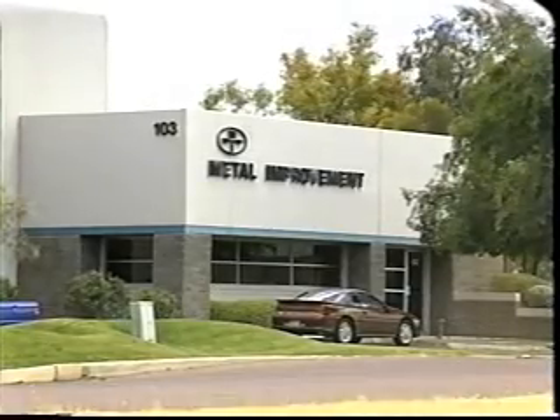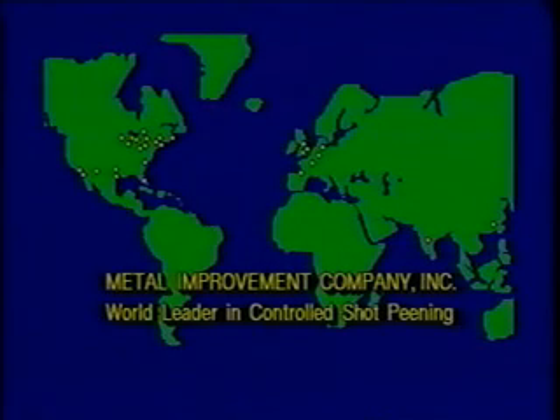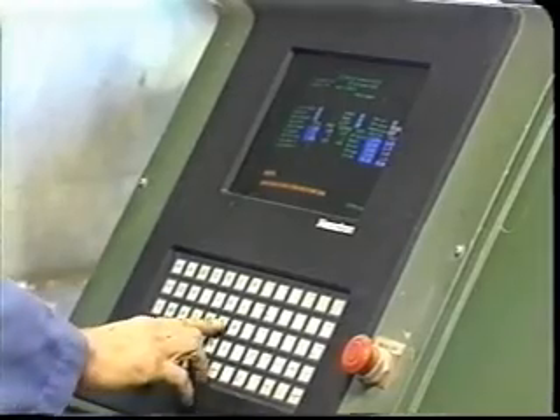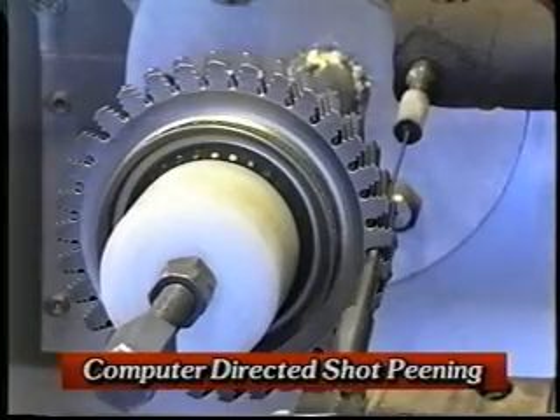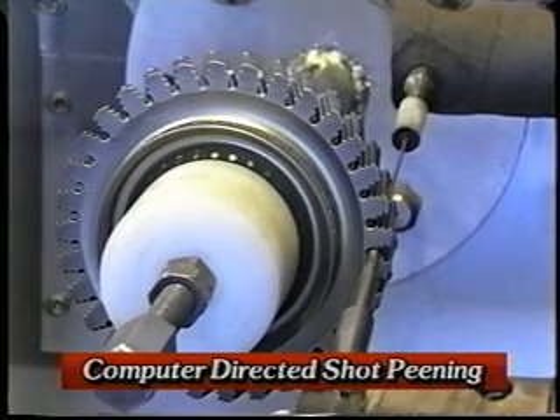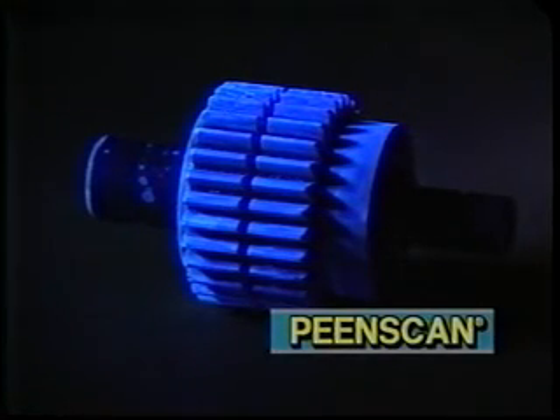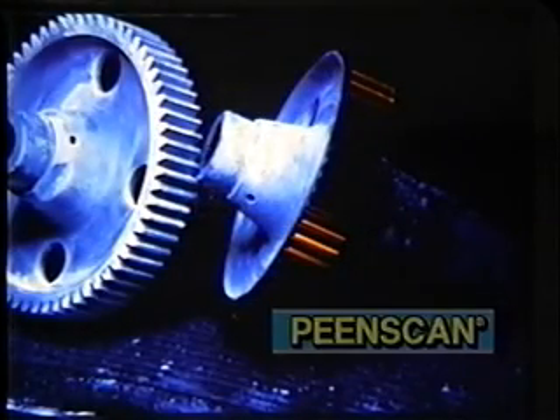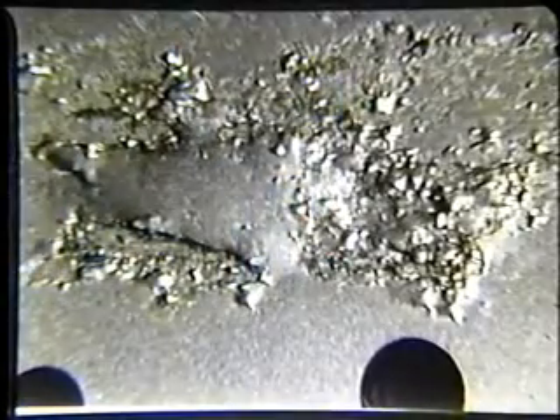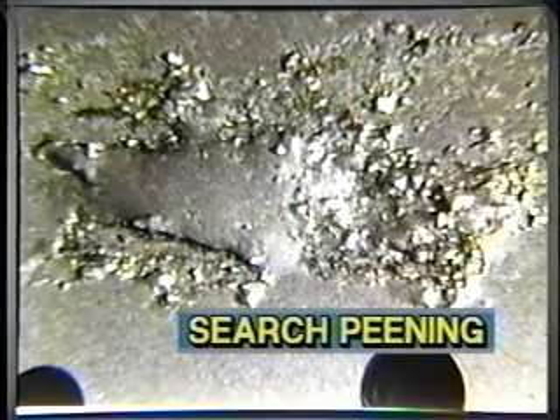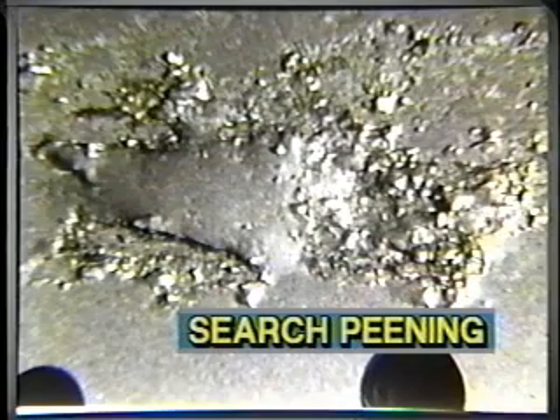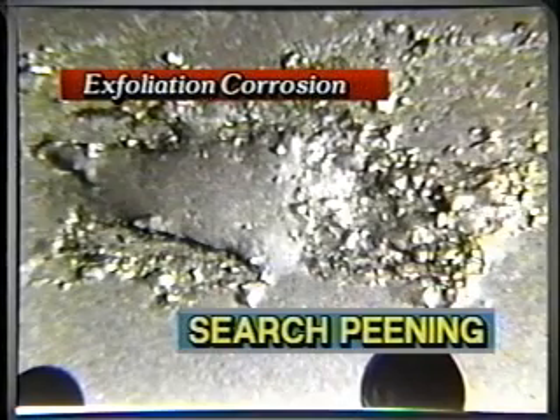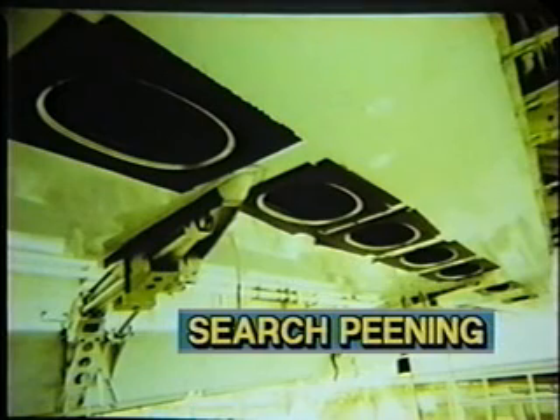Metal Improvement Company is the largest company in the world that processes metal parts on a subcontract basis. MIC was the first to introduce computer-monitored and controlled shot peening equipment for flight-critical components. We introduced and licensed a process called Peen Scan that uses a fluorescent tracer to evaluate shot peening coverage. MIC has developed a unique process called search peening that enables us to positively identify and subsequently remove deep exfoliation corrosion on aircraft wing and tail surfaces that is much more effective than eddy current testing.